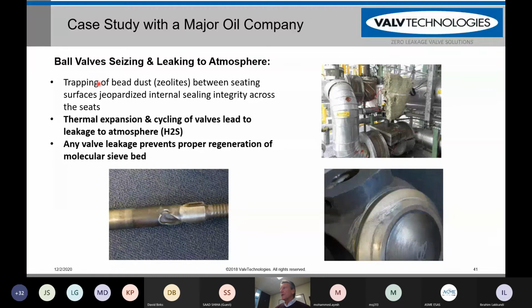So you can see here that this is an actual case study. Again, an end user, a major end user in Kazakhstan, was having a lot of problems with the valves that they were using on this molecular sieve application. The zeolite was getting all up inside the valve, and it caused galling and deformation of the stem and scratching of the seat. Also, you have a bolted bonnet design on this valve that has a different coefficient of expansion than the body. So when the temperature swing happens and the gas passes through this valve, you get severe temperature swings in about 2 minutes time.